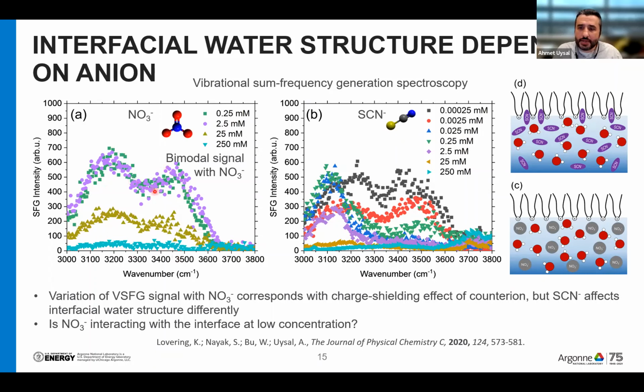But the main difference in thiocyanate, there are two differences. Number one, if you want to see this bimodal signal, you should go to much lower concentrations of thiocyanate. So definitely thiocyanate is much more surface active. As soon as you introduce your thiocyanate, your water signal starts going down because it's coming to the surface much more strongly than nitrate. That's what we can think by looking at this data. But more importantly, your signal is not just simply going down. We lose only around this 3500 band at low concentrations, and the 3200 band gets redshifted and also gets more narrow as thiocyanate adsorbs. Basically, thiocyanate is forcing a completely different water structure at the interface, starting from very low concentrations.